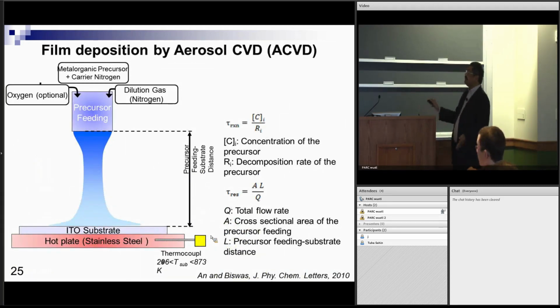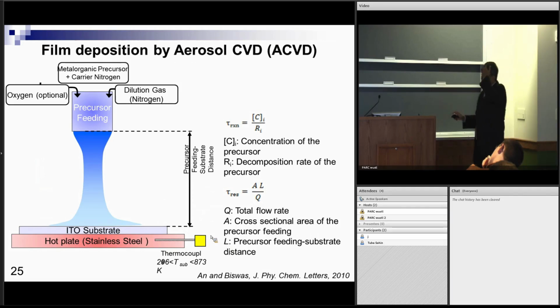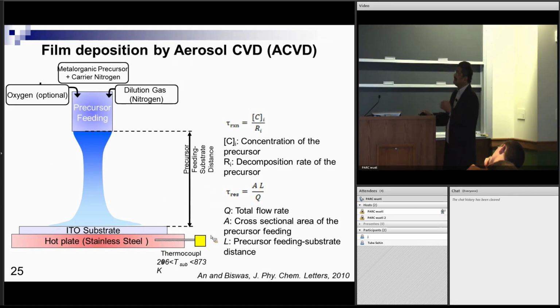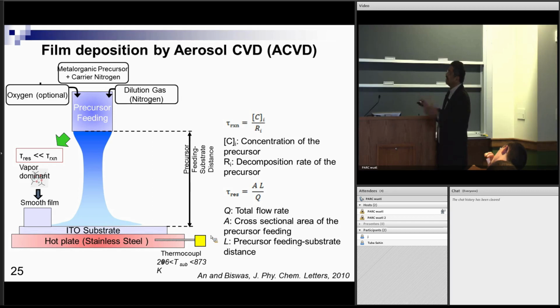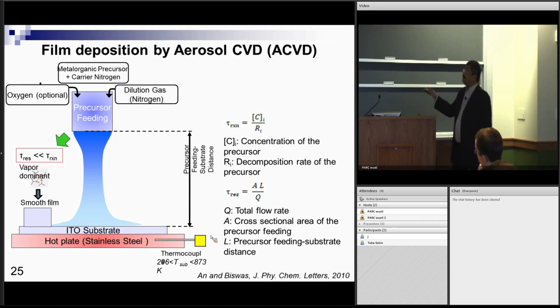I also modify the process. We call it an aerosol CVD technique. Flames are good, but sometimes difficult to control. This is like a chemical vapor deposition process where I heat the substrate, right? I heat the substrate and then control all that is happening. Again, it's a play with all these different time constants, and I won't get into that here, but I have the same kind of thing. So if the residence time is much less than the reaction time, right? By the time I move from here to here, this reaction time is so large, and it all depends on what I choose, what the temperature is. I'm going to just react it on the substrate and get a smooth film.